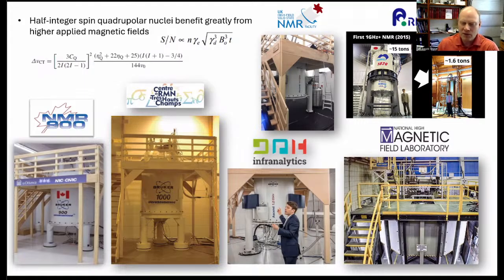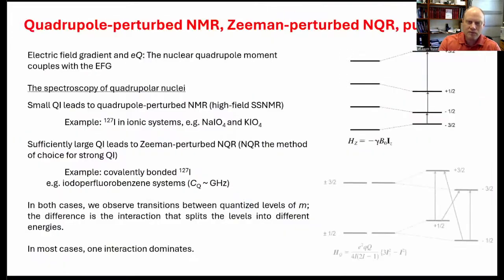So we're up to, for example, a commercial product now from Bruker, 1.2 gigahertz proton frequency. And one of the big reasons for this push, as I say, is for looking at these strongly quadrupolar nuclei, where the signal to noise really goes up with the strength of the magnetic field, and the lines get much narrower with the higher fields, thereby increasing spectral resolution.